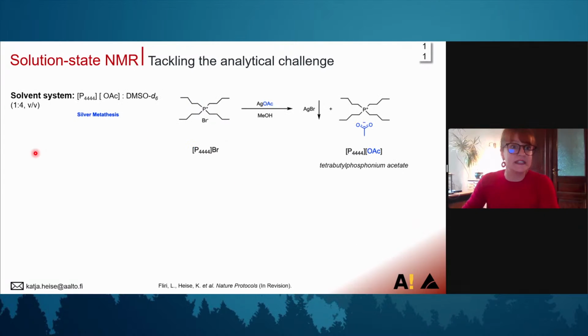Okay, the solvent system that we use, as I mentioned, is an ionic liquid. It's tetrabutylphosphonium acetate, which is used with a co-solvent DMSO in a ratio of 1:4. This electrolyte can be obtained through an optimized protocol now by Lukas Flin from Aalto University through a silver metathesis. And there have been several ionic liquids that were studied in this regard.